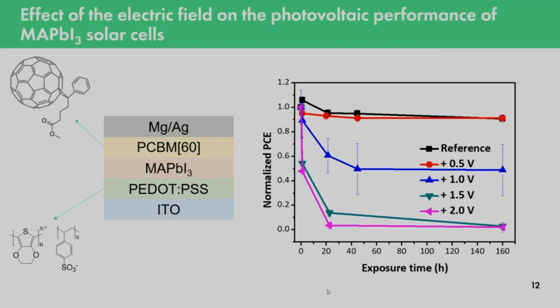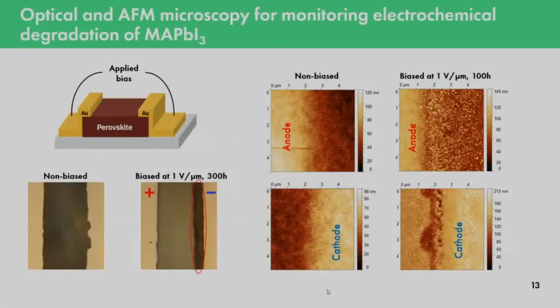We assembled the most model configuration of a perovskite solar cell, which is ITO, PEDOT:PSS charge transport material, methylammonium lead iodide, the fullerene derivative PCBM60, and silver electrodes on top. We applied different voltages to this device, and yes, we observed that applying a voltage of more than 1 volt led to the degradation of the device. So probably there is some threshold voltage, because all voltages lower than 1 volt didn't lead to any changes in device efficiency.